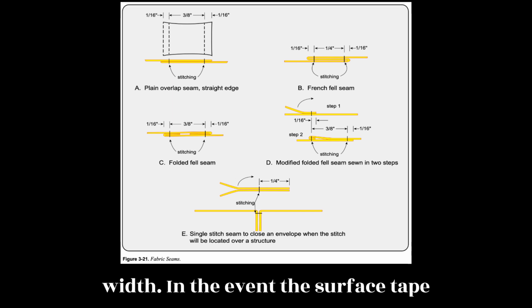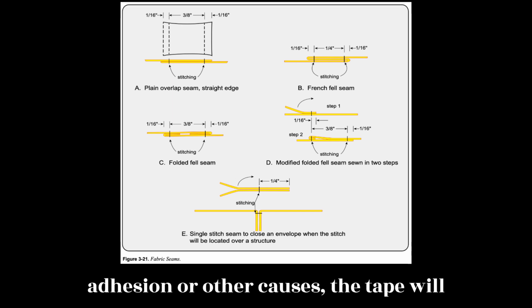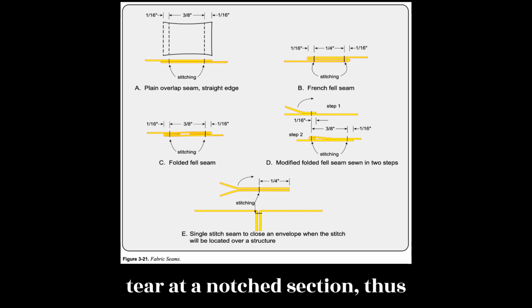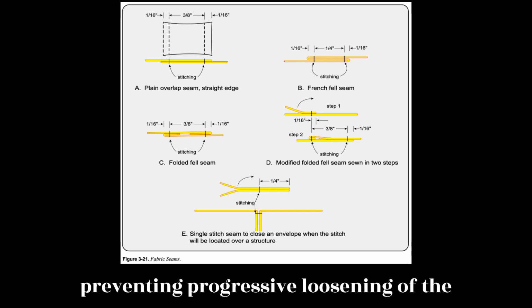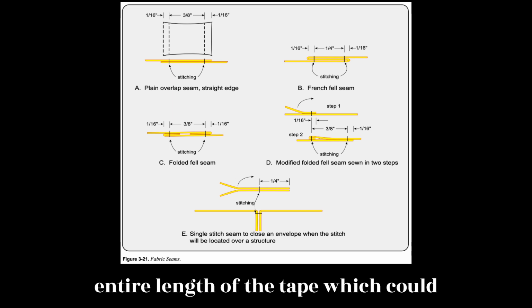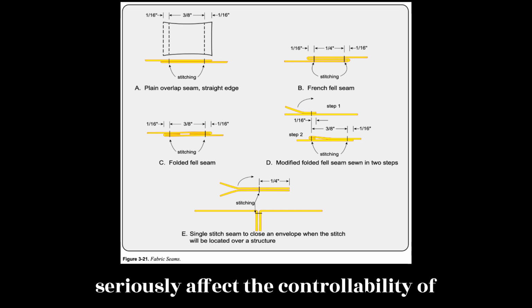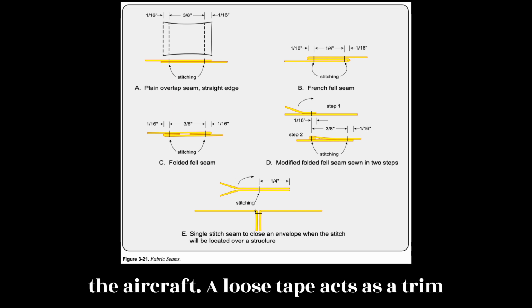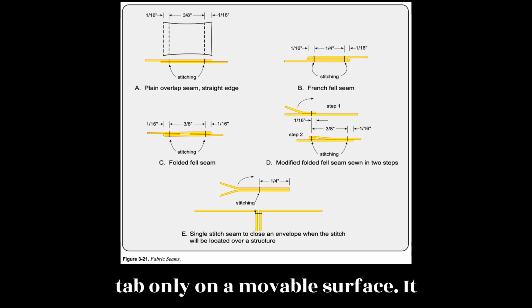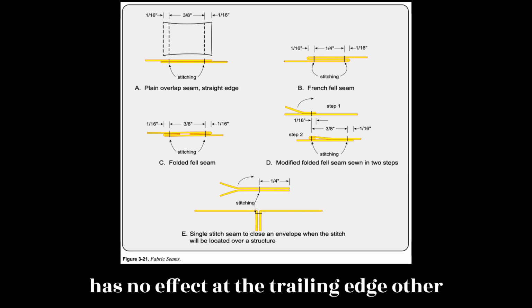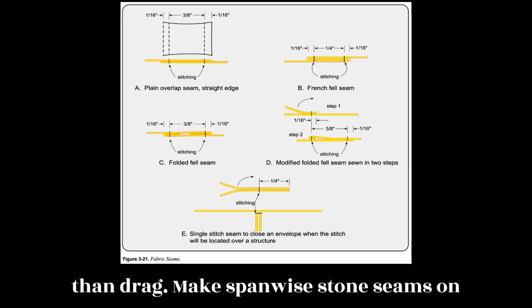In the event the surface tape begins to separate because of poor adhesion or other causes, the tape will tear at a notched section, thus preventing progressive loosening of the entire length of the tape, which could seriously affect the controllability of the aircraft. A loose tape acts as a trim tab only on a movable surface. It becomes a spoiler on a fixed surface and has no effect at the trailing edge other than drag.